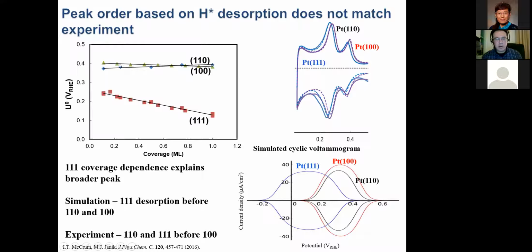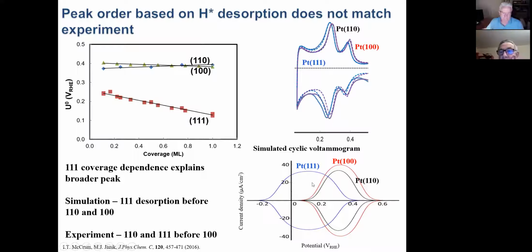Some things agree very well with the experiment, like the adsorption is no longer coverage dependent. And what we see there is that we should then get sharper peaks because all of the hydrogen wants to come off right around the same voltage. And that is true experimentally, you get much sharper peaks. However, we don't get the position of them right. 110 and 100, the peaks should be in exactly the same place based on how strongly hydrogen adsorbs. We also don't get the height of them right. We actually still get them a bit too broad. So we must be missing something.